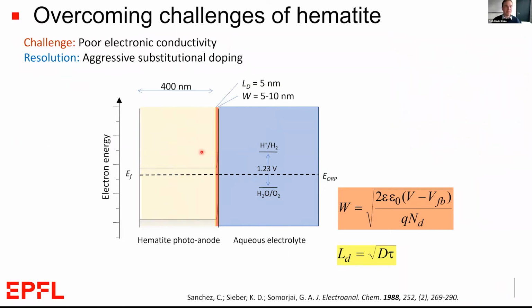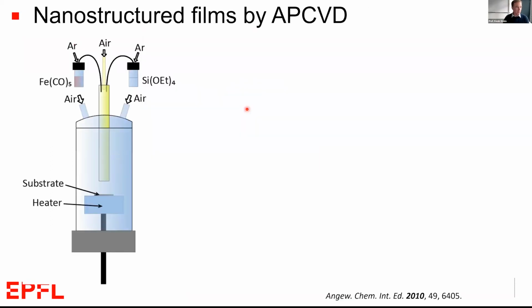But for the case of hematite, the situation looks really, really bad. We need about 400 nanometers of thickness of a film to absorb all of the light in hematite. But based on the amount of doping that we need and the diffusive transport properties, we only have light carrier harvesting from the first about 10 to 15 nanometers. What that means is that we need to nanostructure the material.